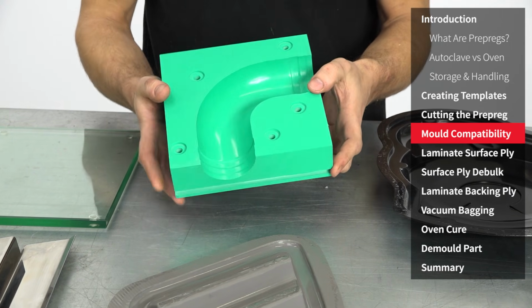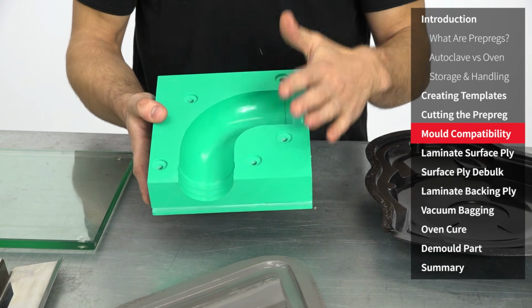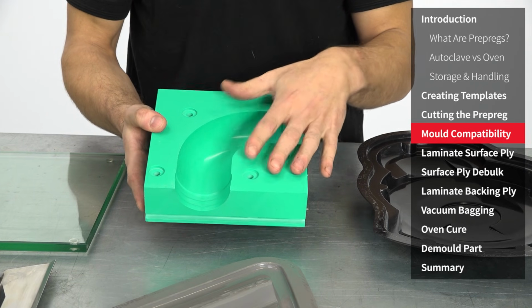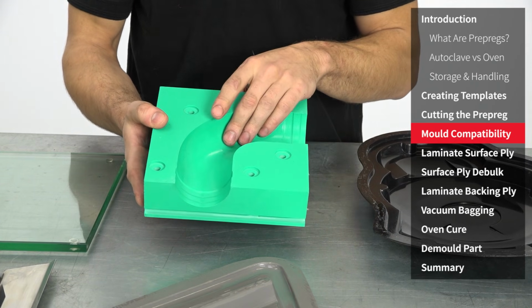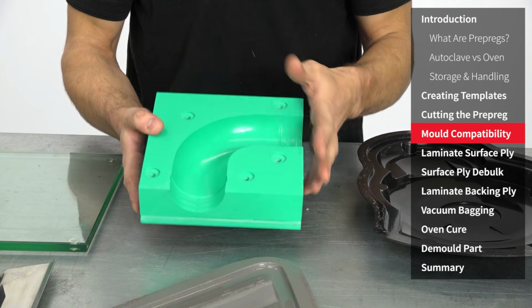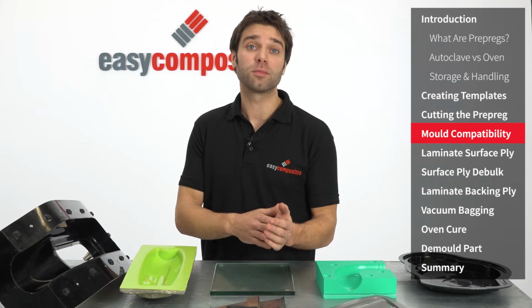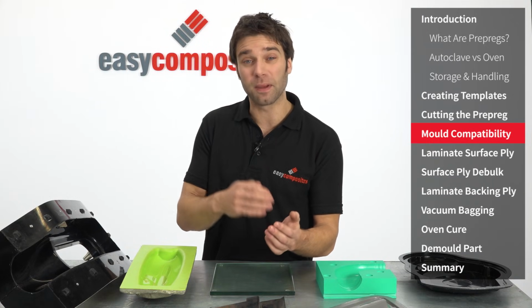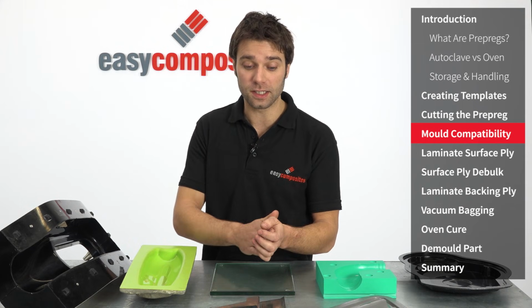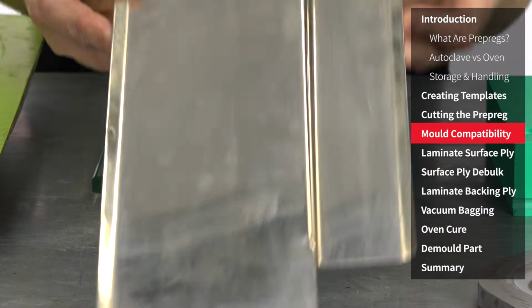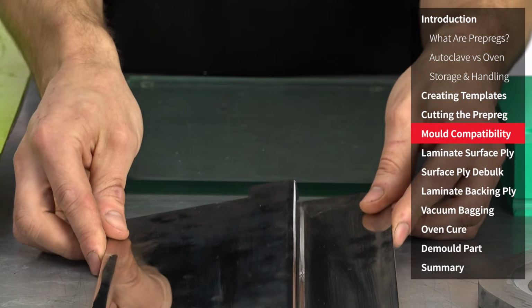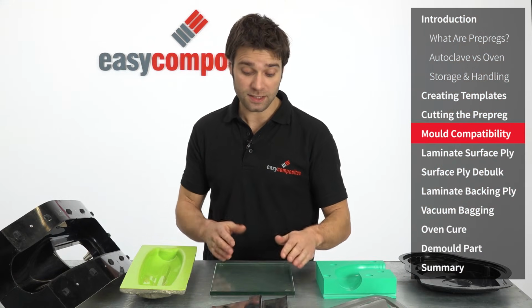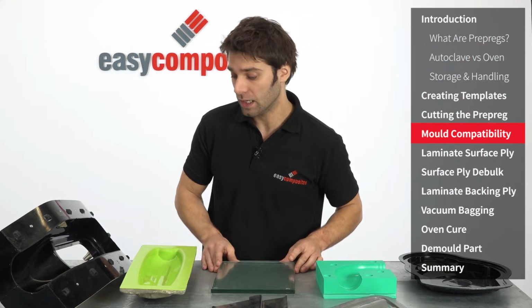Then for short production runs or prototypes, you can work directly from epoxy model board. So this has been sealed with the S120 sealer, and this could be used directly as a mould. Other highly compatible tooling surfaces can be metals, so that could be aluminium, steel or stainless steel, which could be either folded into a mould tool like this or machined into a full mould. Or for producing flat plates, glass is absolutely ideal.